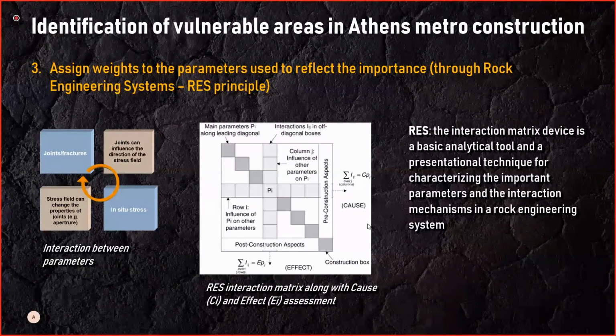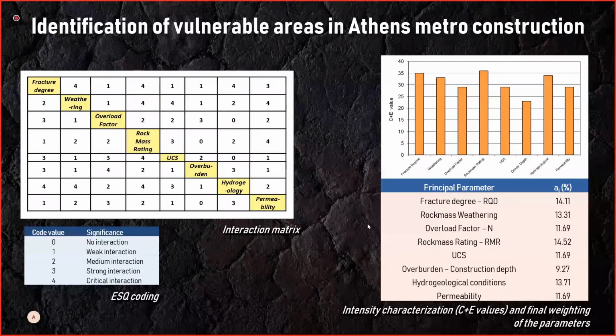To this end, a weighting of these parameters could be most appropriate in order to have a unique value that can characterize the vulnerability. In our case, we have used the rock engineering system principles as given by Hudson, and the interactivity of the parameters is the indicator of the importance of the system, and so the method has been selected to do so. Of course, someone else could use some other multi-criteria analysis, such as the analytic hierarchy process, to prioritize the parameters. Here you can see the matrix that was developed and the ESQ empirical semi-quantitative rating that was applied to come up with the results given in the table.